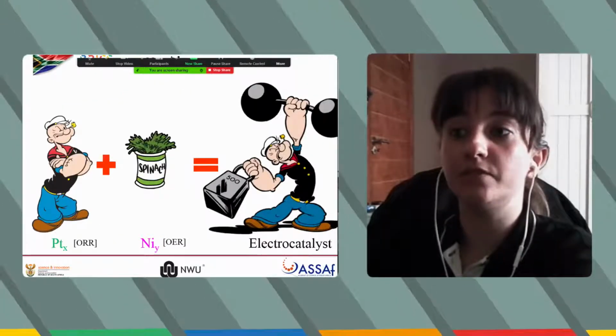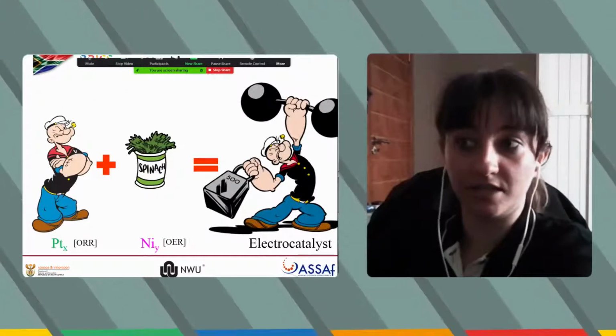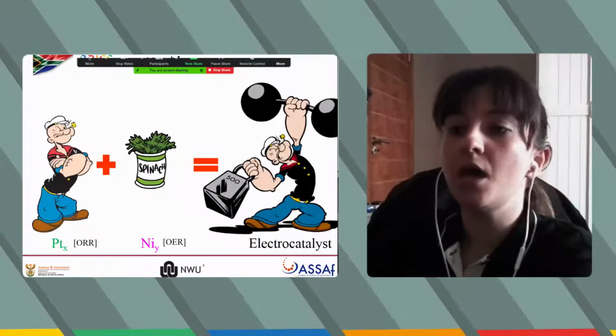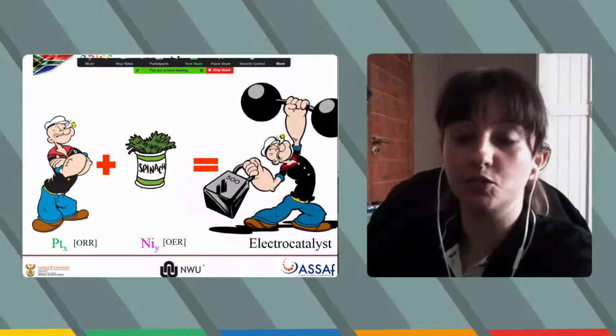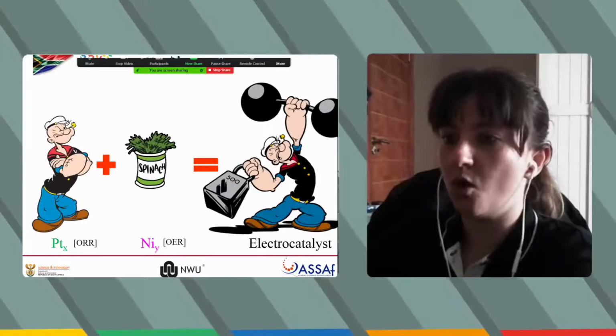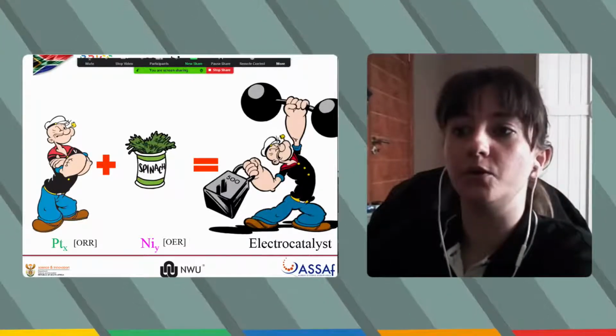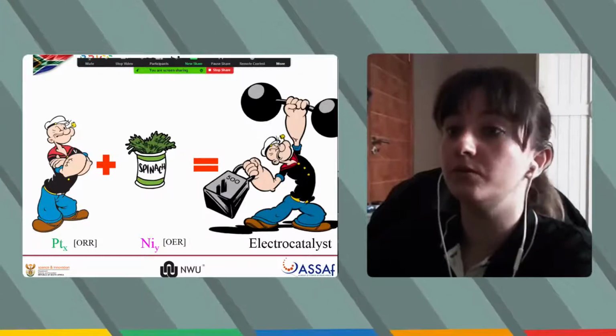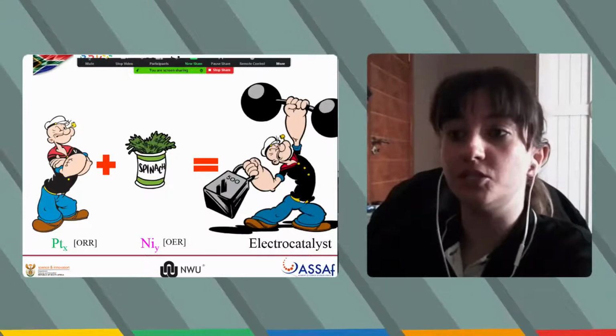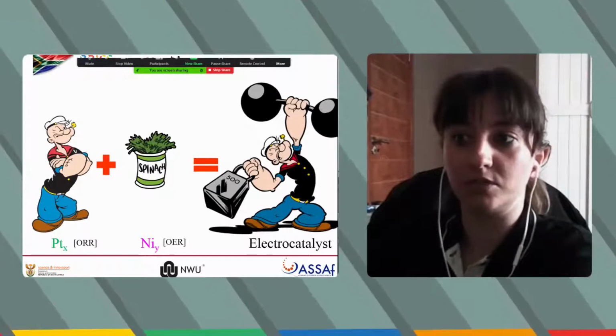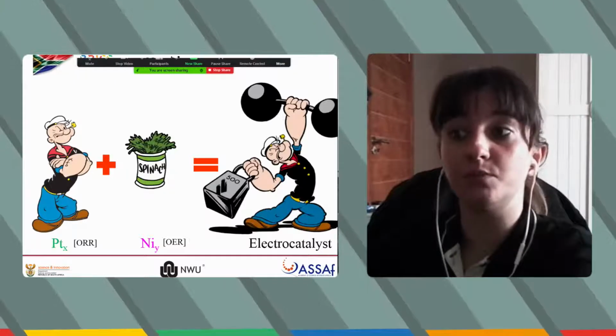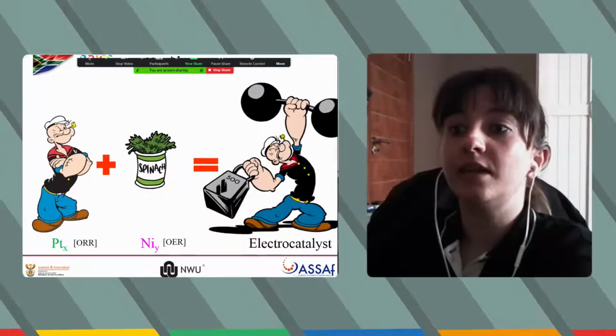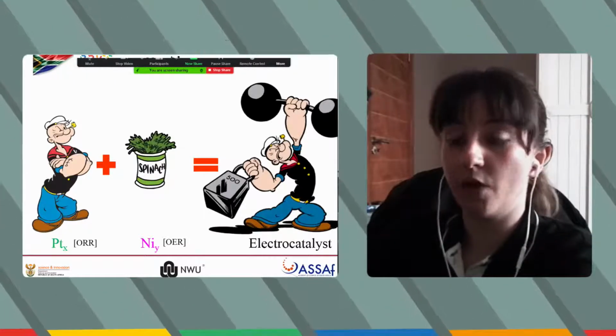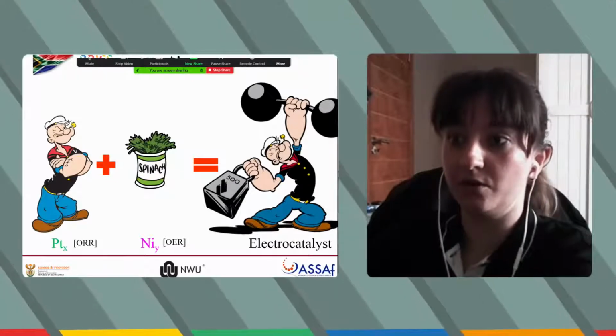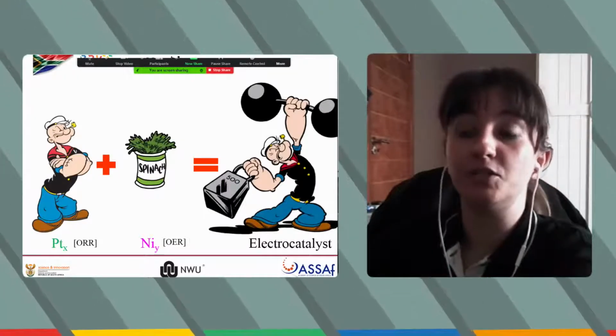The aim of the study is to develop cost-effective electrocatalysts for these two reactions. Platinum is a good electrocatalyst towards the oxygen reduction reaction, while nickel oxides are good electrocatalysts for the oxygen evolution reaction. From literature, platinum-nickel nanoparticles have been identified as possible electrocatalysts that can be used for both these reactions. However, the best mixing ratio of platinum and nickel has yet to be determined.